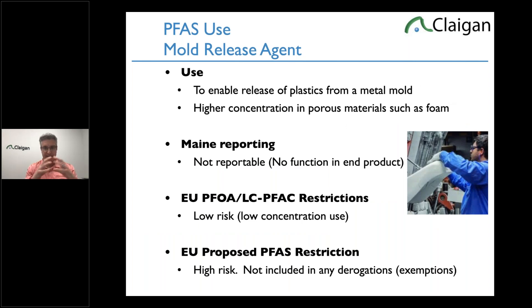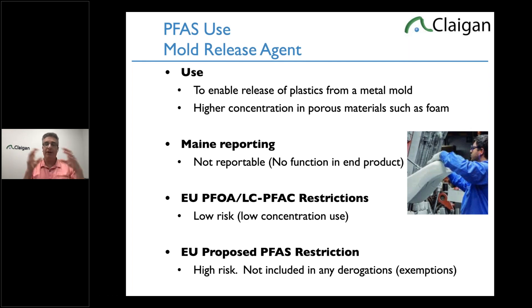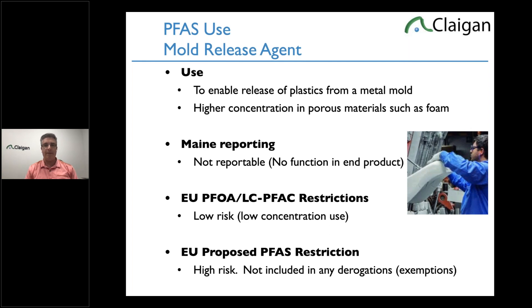To summarize mold release agent: it enables the release of plastics from a metal mold, usually applied as an aerosol spray. It's at much higher concentration in porous materials such as polyurethane foam versus closed-cell polyethylene foam like pool noodles. Polyurethane open-cell foam sucks up a ton of mold release agent. For Maine reporting, it's not reportable — it is not intentionally added because it has no function in the end product. For PFOA risk, the concentration is so low — if it were solid PTFE at 40% fluorine, you'd only get a couple hundred parts per billion PFOA, which is just a trace contaminant.